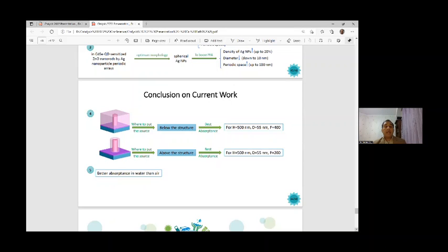About the conclusion of our current work, we compare two structures, 2 and 3. For structure 2, the direction of sunlight should be above the structure, but for structure 3 it should be below the structure for the best absorption and performance. According to curves and simulations obtained from the FDTD simulation method, a TiO2 nanorod height H equal to 500 nanometers, diameter D equal to 55 nanometers, and center to center spacing P equal to 400 nanometers is the best. We have achieved the best performance,